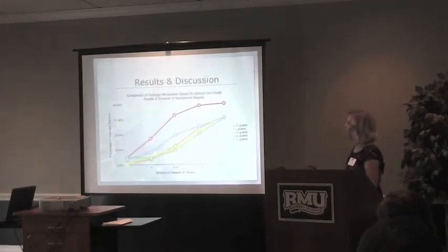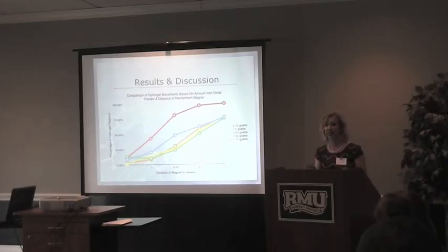So when I did this, I measured each of the concentrations and distances away, and then figured out the percentage of the gels that moved. This is a chart showing each of the concentrations of the powder along with the distances away of the magnet. And the red line, which is the highest movements, is 1.75 grams of the iron oxide powder in the hydrogels. This isn't really a surprise that this was the highest movement, since it is the highest concentration.